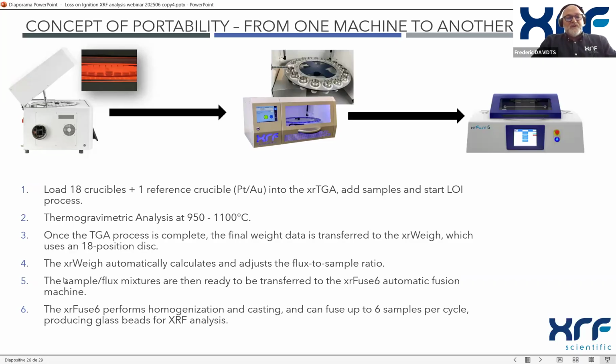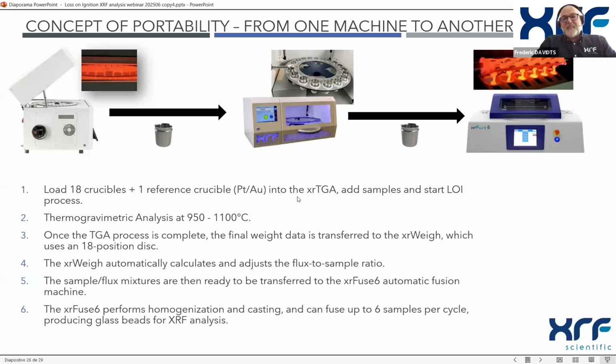And then we'll transfer the sample-flux mixture directly to the XRFuse 6 for the automatic preparation of fused beads ready for XRF analysis. The big advantage of this system is that we can use the same crucible for the TGA, for the xrWeigh, and for the XRFuse 6. So we have what we call portability.